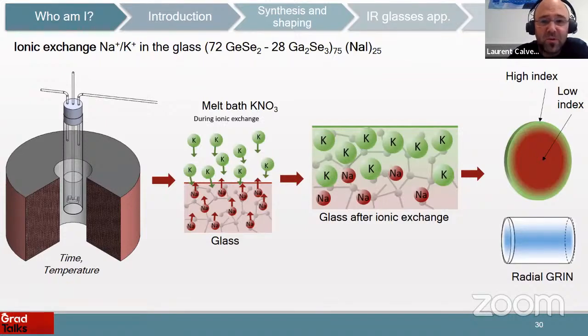because I told you that we want to avoid oxide within the glass. Well, what we have shown is that even using a nitrate bath, it's only the potassium which will enter the glass and not the oxygen. So we will have a different glass composition, and the potassium can enter the glass. At the end, we will have a high refractive index in the middle and a low refractive index on the side. So we will have a gradient of refractive index in our glass.